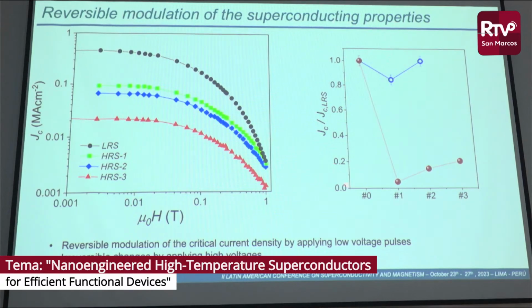Here, showing JC as a function of the switching procedure, we see that if the switching introduces small changes in JC, this is reversible. It can be changed and come back to the initial state. But when we change the JC by a large amount, like in this case, for example, we go from this system to the red one, when we want to come back to the pristine state, we are not able to recover the JC completely. We can just go to these two intermediate states because there are several irreversible changes that we introduce in the material if we do it very large; we introduce a lot of oxygen vacancies in the system.